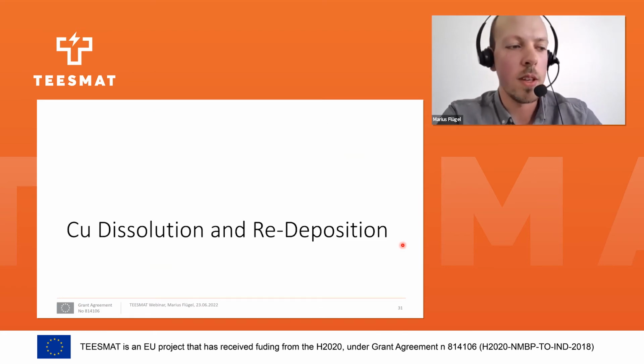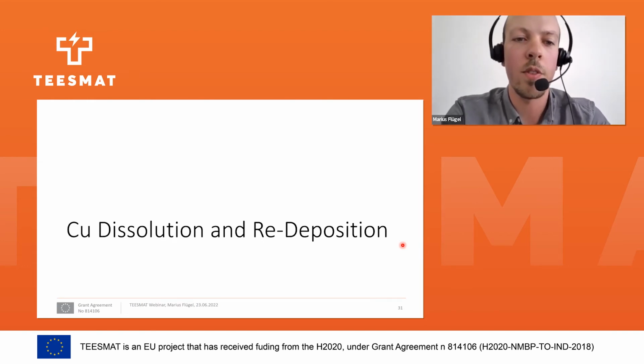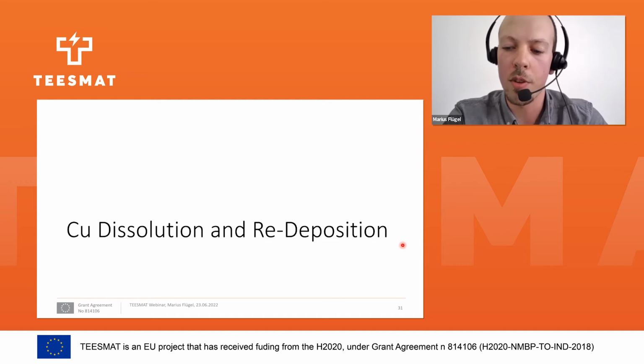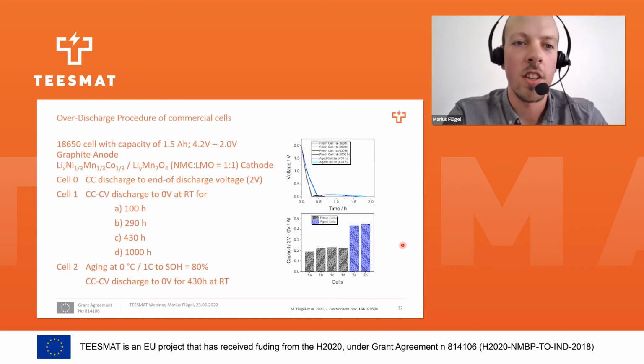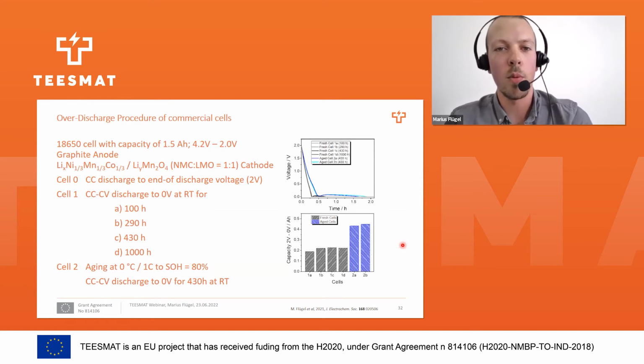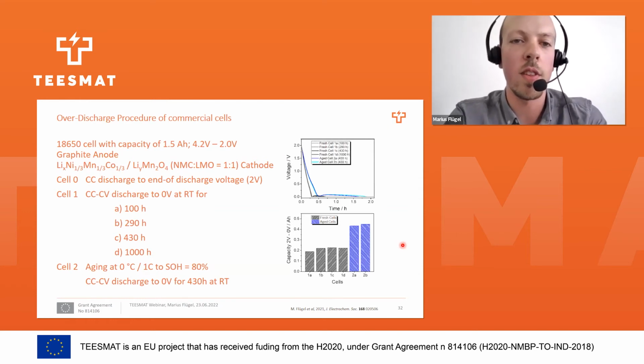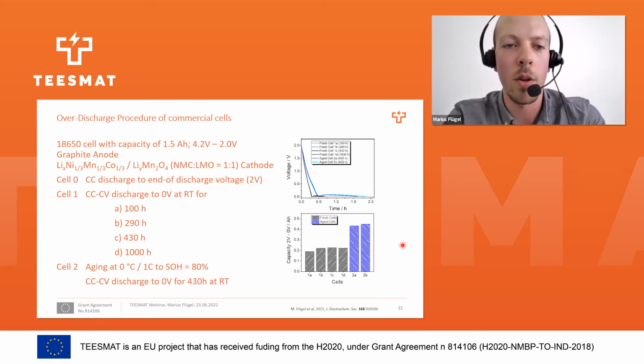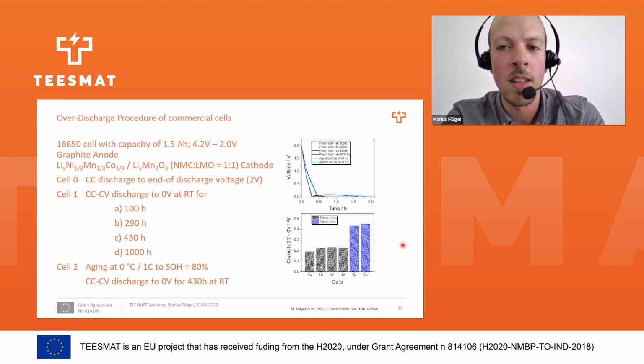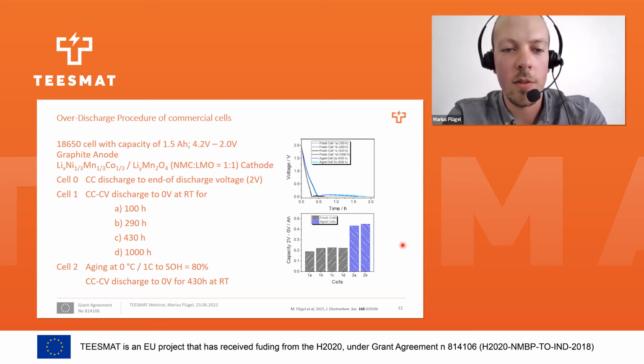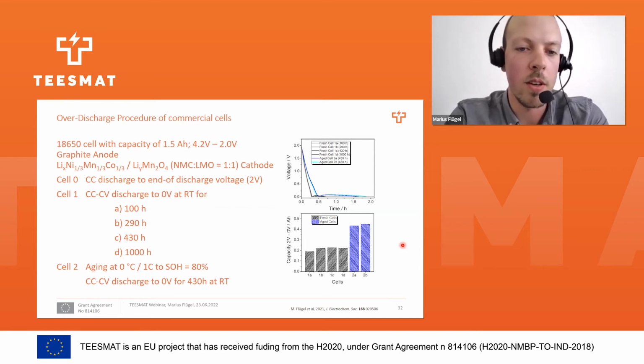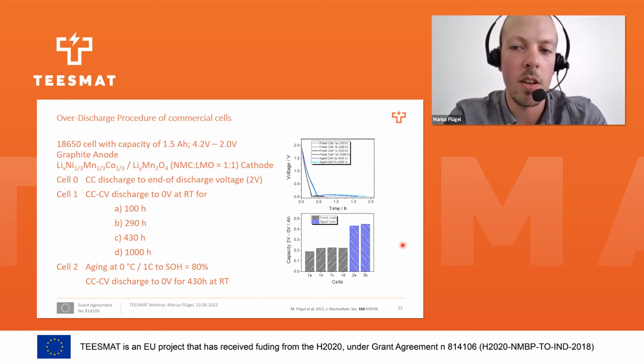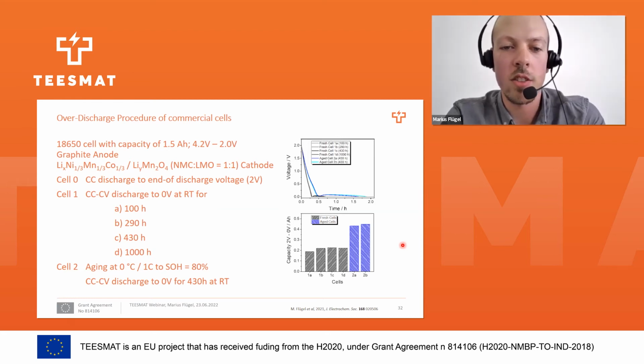Our method can also be used to investigate copper dissolution and redeposition after over-discharge. For this experiment, we also used 18650 cells, which were over-discharged to 0 volts for a different amount of time: 100, 290, 430, and 1000 hours. And also a second set of cells was used, which, simultaneously to our previous experiment, was first aged, however, this time at low temperatures, and then over-discharged to 0 volts.